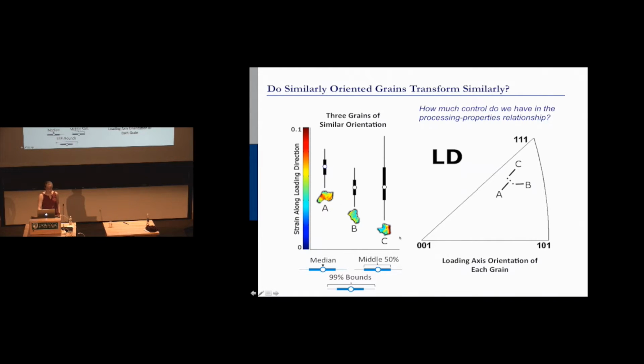These are all super similarly oriented. This one has kind of the same strain range, but much lower strain, much lower overall transformation. This one has the same overall transformation, but it's much more heterogeneous, right? You've got a much higher strain range. So not only do they not transform similarly, these grains are all pretty much oriented the same way, they don't transform similarly in the amount that they're transforming, and they don't transform similarly in the distribution of how they're transforming in either metric. Those are only three grains.